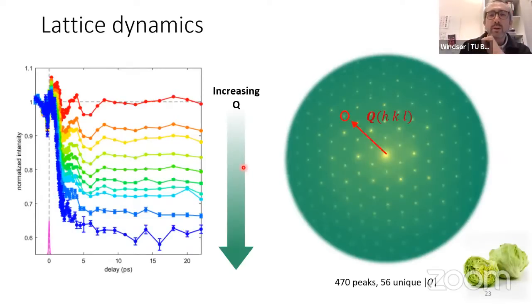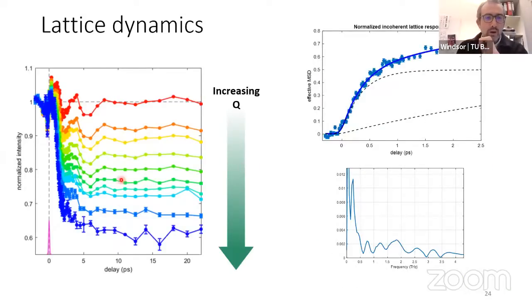And so if we then look at these two observations, one is this drop and the other one is these wiggles, we get these two graphs. One of my colleagues told me that this axis might actually be a tiny bit wrong, so that happened this morning. But what I want to focus on is this. What do we see here? We see here what I call an effective mean square displacement, which I will now explain. This drop in intensity happens because our atoms spend less time at their nominal high symmetry position. And they spend less time there because they vibrate more as more energy is passed into the lattice because of a growth in phonon population. So what we see here is a description of that.